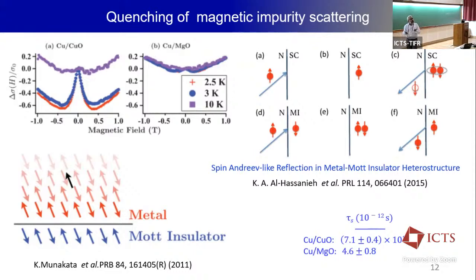And so the spin flip scattering decreases because it costs some energy. Only when you raise the temperature could there be spin flip scattering. Since there is an interaction between the impurity spin, the black one, and the polarized spins of copper, it is energetically not favorable to have this spin flip scattering. But when you are growing copper on a band insulator, no such scenario happens. So what they find is that the spin flip scattering time anomalously increases when you just grow a metal on top of an antiferromagnetic insulator. So the idea became more clear in 2015.